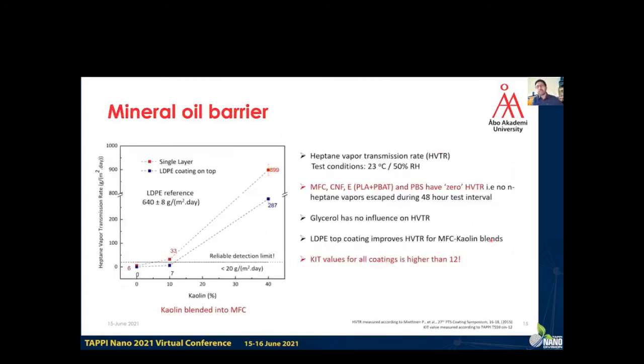Moving on to mineral oil barrier, we measured heptane vapor transmission rate at 23 degrees Celsius and 50% relative humidity. Pure nanocellulose coatings, Ecovio and PBS have 0 heptane vapor transmission rate. That is, no gas escapes even during the 48-hour test interval. Glycerol did not show any influence on heptane vapor, but clay addition to MFC reduces the barrier, or increases the transmission rate. The red one is just for the pure nanocellulose coating, and the blue is when we have LDPE coating on top.